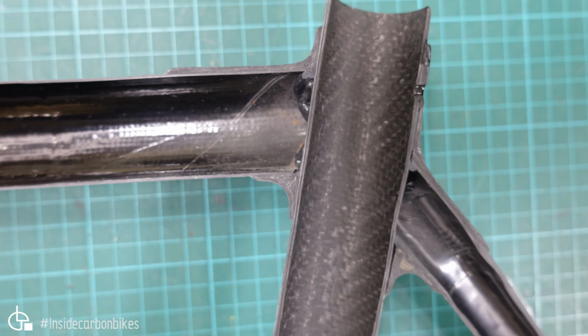Moving to the lug at the seat and top tube junction. Again, there's lots of adhesive through here, and that's good. You can see a little bit of a void in the lug through there, and some wrinkling through here. But there's a big void through here, and a smaller one there, and then here as well. So yeah, again, the one down here, I mean, that's a large void, and it's just about open to edge. So it doesn't seem to be much holding that lower edge together.